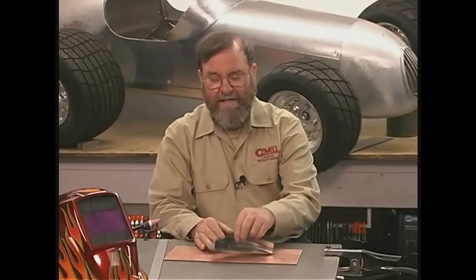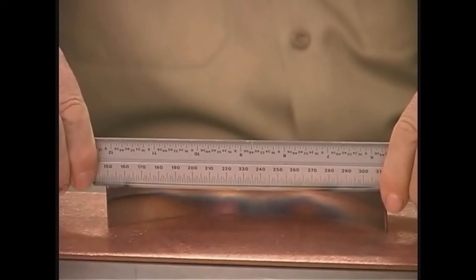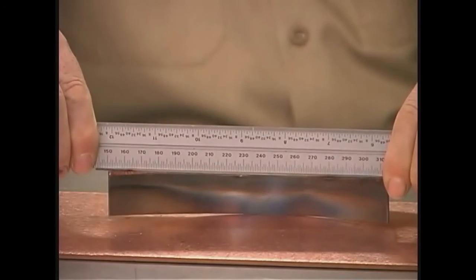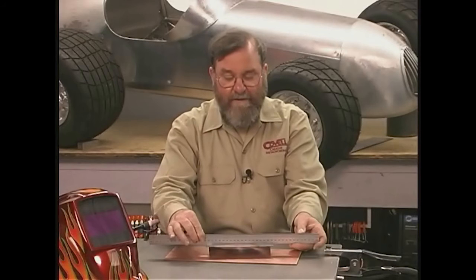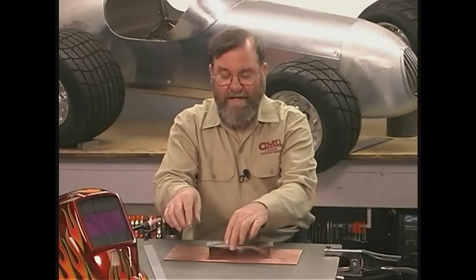Or in situations where you need to build up a lot of weld bead, silicon bronze is very good for filling. Let's talk about the distortion in a little more depth. So I've welded two pieces together using silicon bronze filler rod, and by putting a straight edge on the bottom, you can see that I have very little distortion of the flat piece. Had I used steel filler rod for that application, there would be a great deal of distortion. So that's one of the situations where the silicon bronze rod is truly superior. You might want to experiment with this.